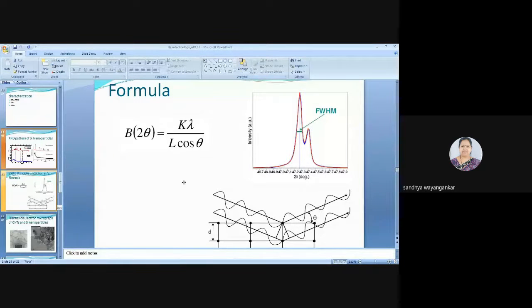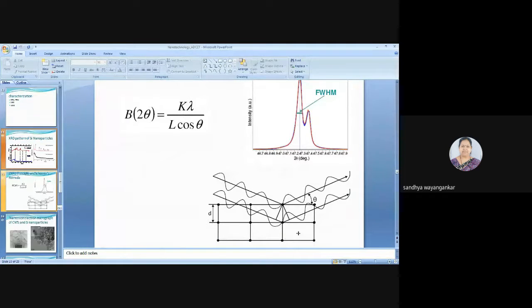The significance of this is how the diffraction takes place. An X-ray radiation incident on the plane hits the atom here and gets diffracted. Another X-ray hits another atom in the sequential plane and again diffracts here. The angle of diffraction is theta. Because of the constructive interference, you see a very sharp peak. In that case, this is crystalline. There will be another coming from here also. And d is the distance between the two planes. This is what you can calculate using Scherrer's formula, or you can validate it using a TEM structure. I'll show you in the next slide.